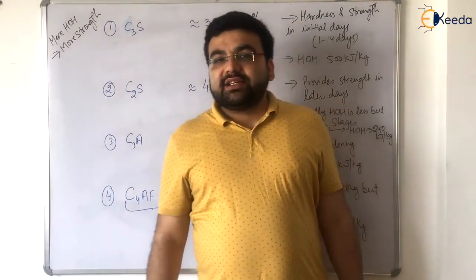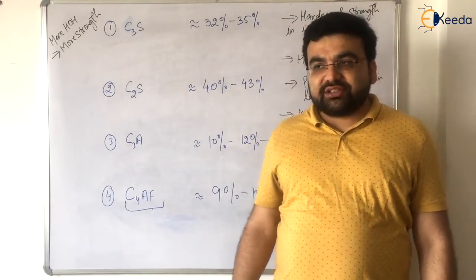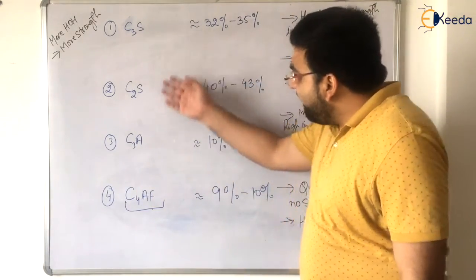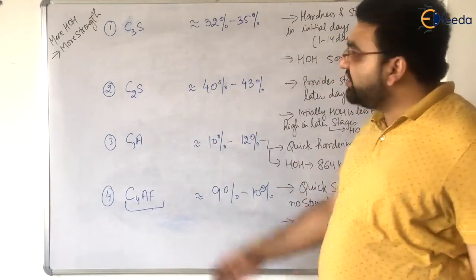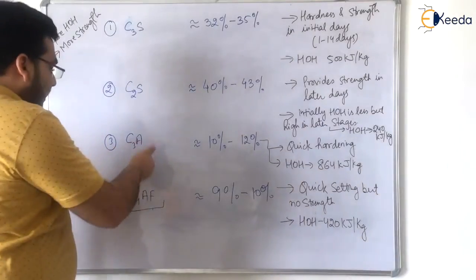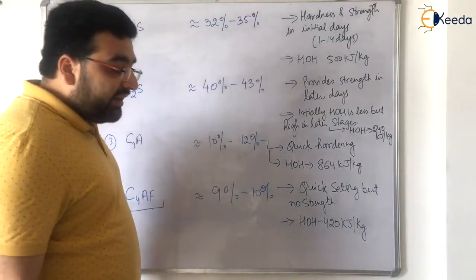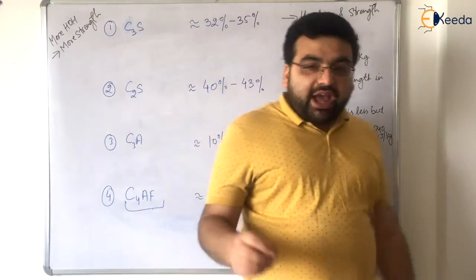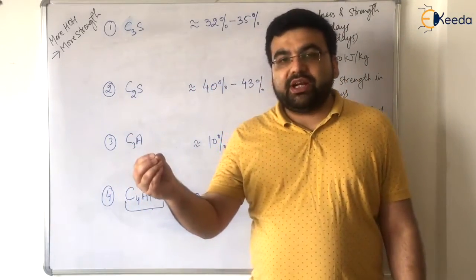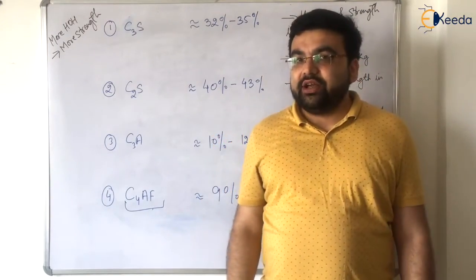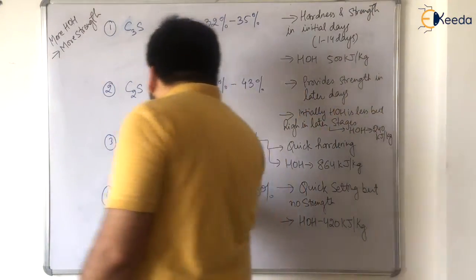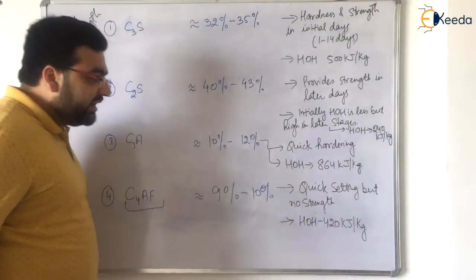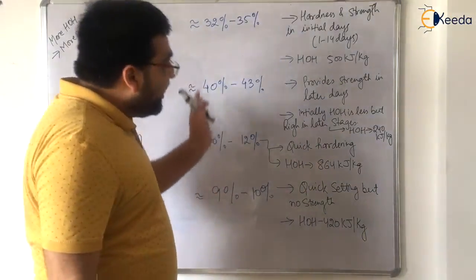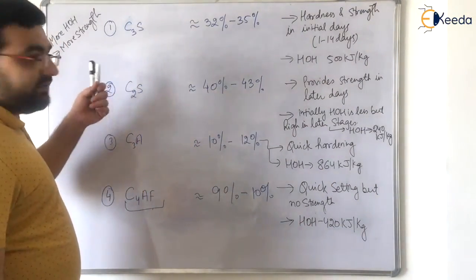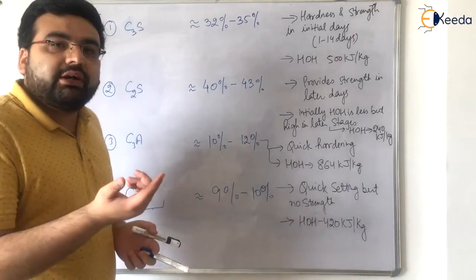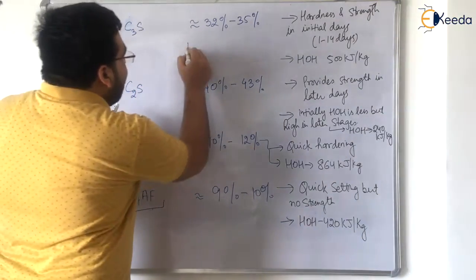Now the question is, sir, if heat of hydration is directly proportional to strength, why don't we have maximum percentage of C3A instead of this C2S or C4AF? What is the reason? The reason is that, for example, if you have a benefit from a particular component, you will also have a disadvantage of that component, right? Because let us say that C3A, it gives the maximum heat of hydration, 864 kilojoules per kg. If we increase the component of C3A, what will happen? These will decrease. See, because ultimately how much should be the overall percentage? The overall percentage should be 100%.